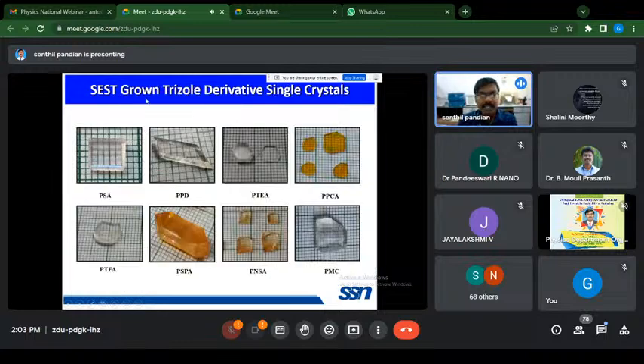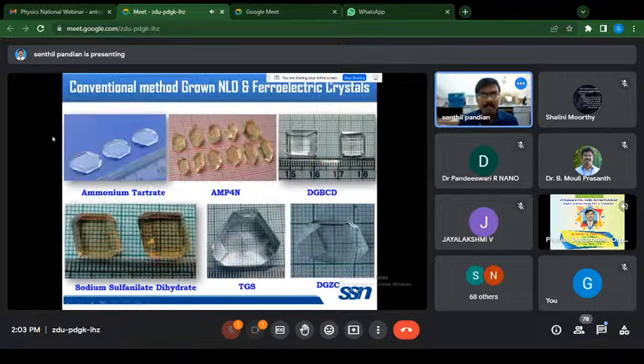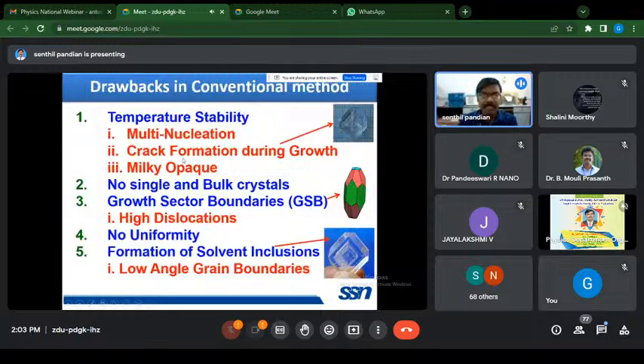This is some of the conventional method grown triazole derivative single crystals grown by the conventional method. You see, the very small size crystal can be grown by this SEST method. For application point of view, you have to grow the large size unidirectional method grown crystal. And these are the conventional method grown nonlinear optical and ferroelectric single crystal like ammonium tartrate, AMP4N, diglycine barium chloride, sodium sulfanilate dihydrate, triglycine sulfate, TGS, and diglycine zinc chloride single crystals for SHG application.